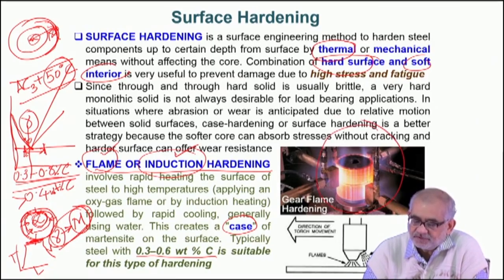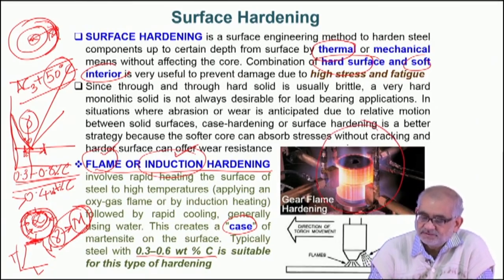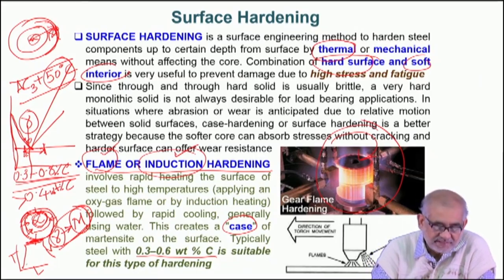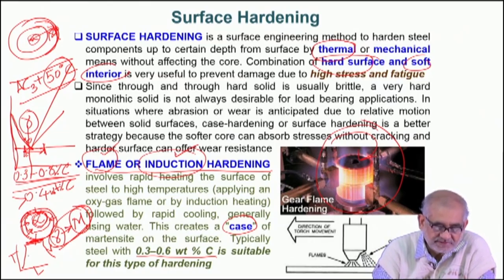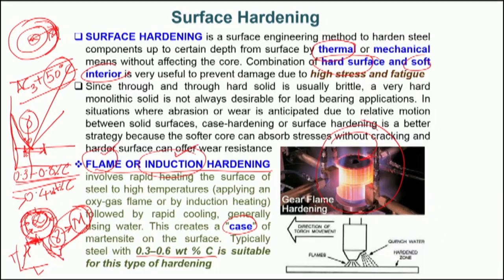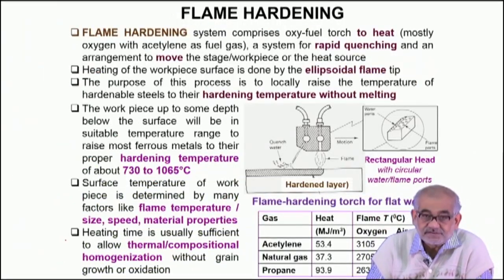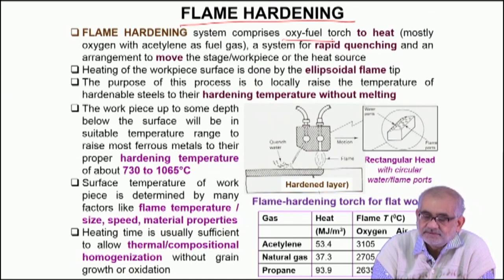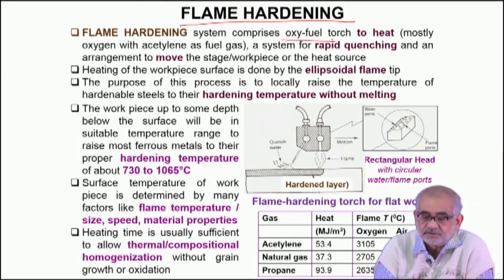Here is a real-time picture showing a very large gear subjected to flame from multiple sides while the assembly rotates at a particular speed, so the entire surface is exposed to high temperature in turn. This is the kind of transient heating cycle the surface experiences — we allow a certain residence time, but the heating is brief. Subsequently, we quench using some kind of quenchant. For flame hardening, we can use an oxy-acetylene or some other form of flame.